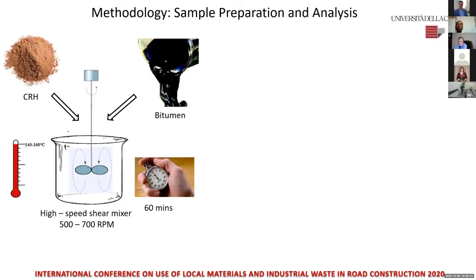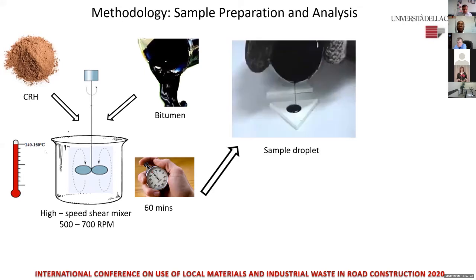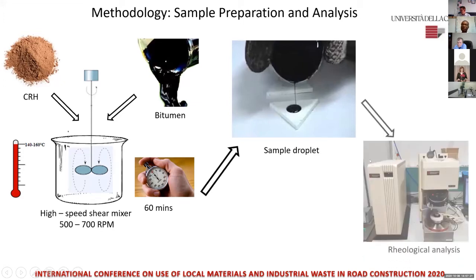Now, how we prepared our samples, it's quite easy to prepare the samples. You add the CRH additive, which is in the form of a powder, to the bitumen, and you add it into a container with a high-speed shear mixer at the RPM between 500 and 700 at a temperature of 140 to 160 degrees, and you leave under agitation for 60 minutes. After the preparation of the sample, you take some sample droplets, which is this, and you take it to rheological analysis.